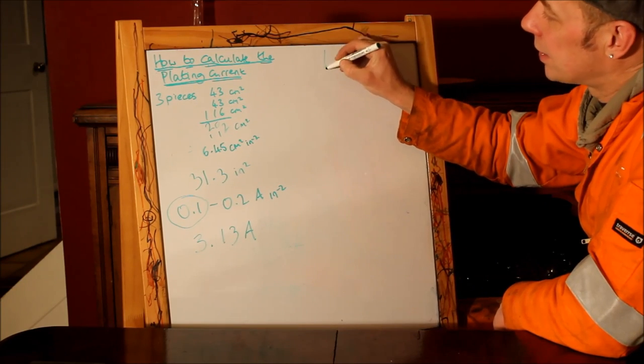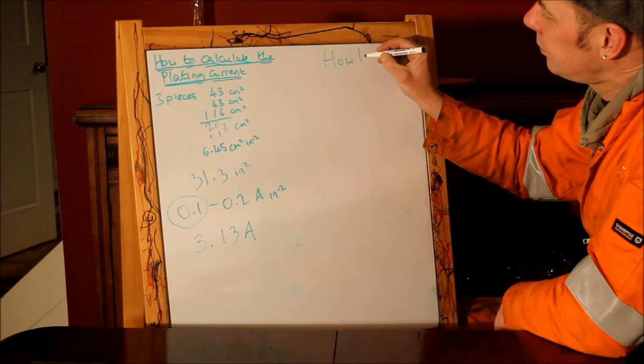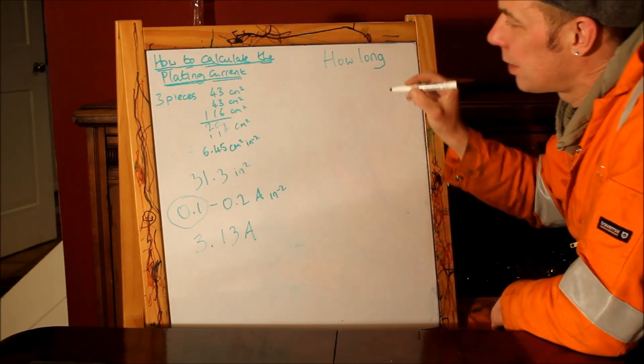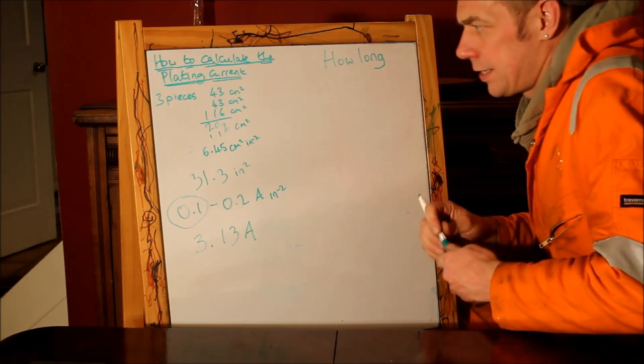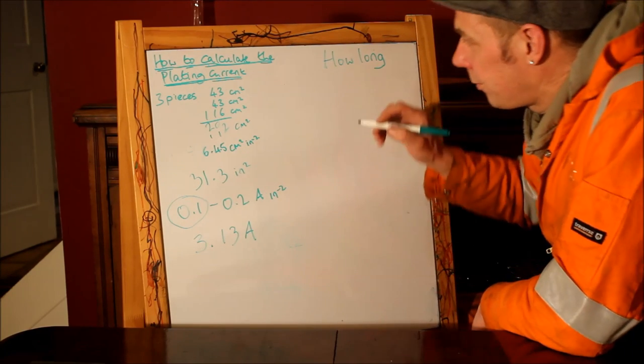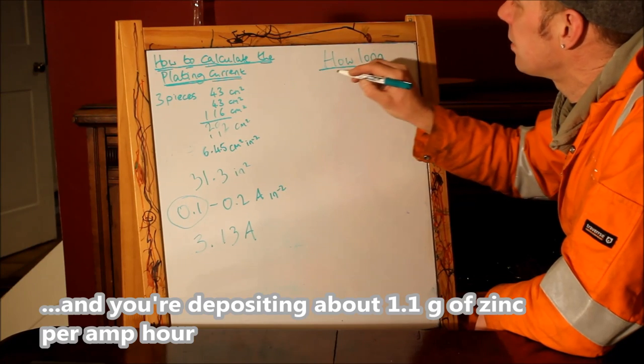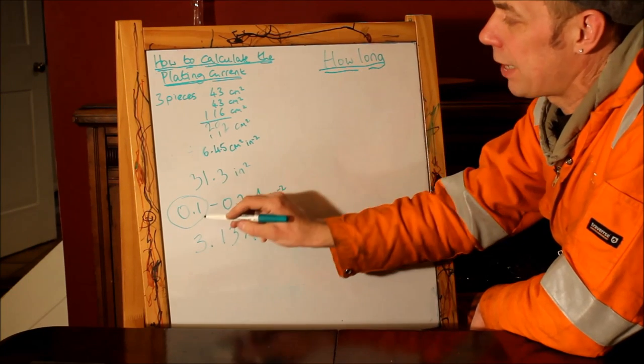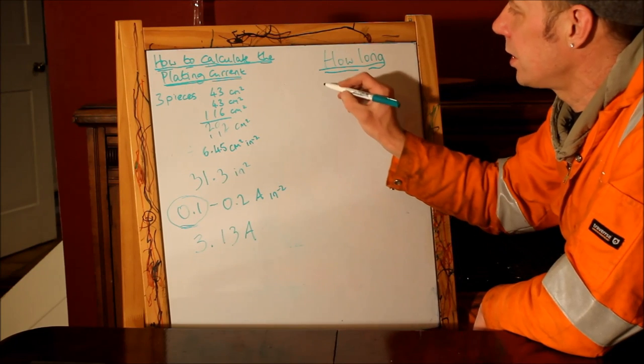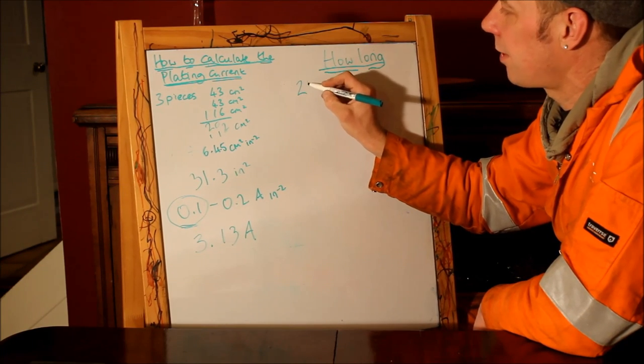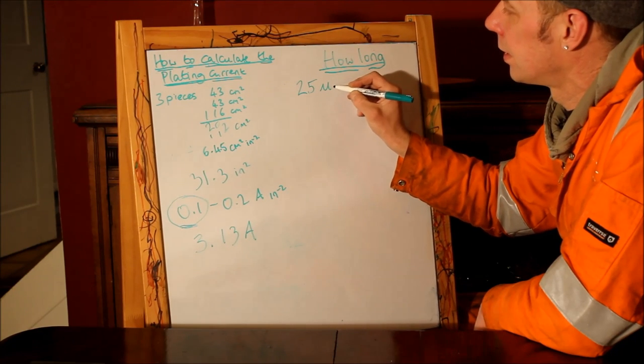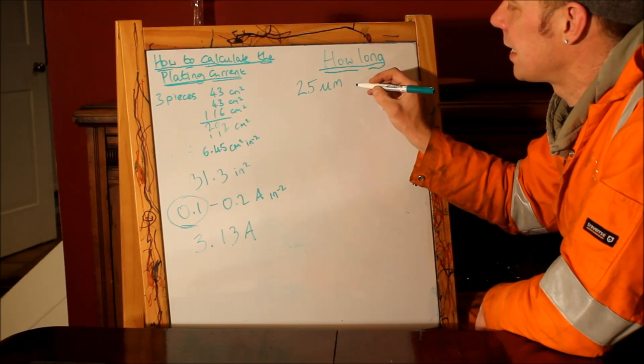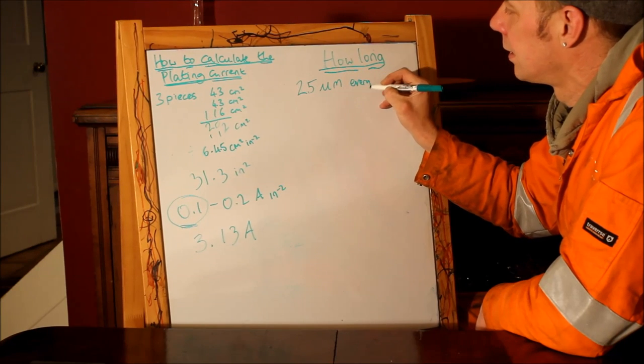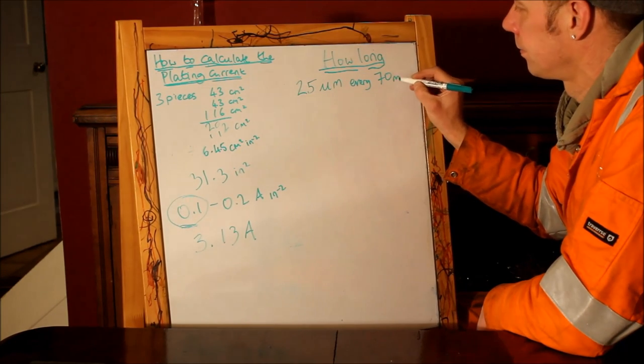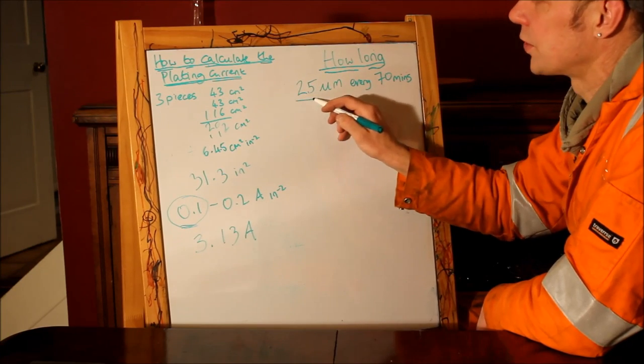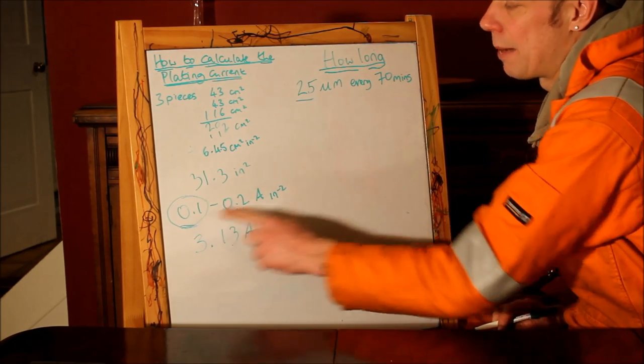Now the other thing is, how long is it going to take? Now, if you want to work this out, you'll need to know that the density of zinc is, I believe, 7.14 grams per cc. If you don't fancy working it out, then just take my word for it. If you plate at 0.1 amps per square inch, then you'll deposit 25 microns, so that's 25 thousandths of a millimetre, every 70 minutes or so. Okay? And that would be a normal sort of plating thickness. So that's if you plate at 0.1 amps per square inch.